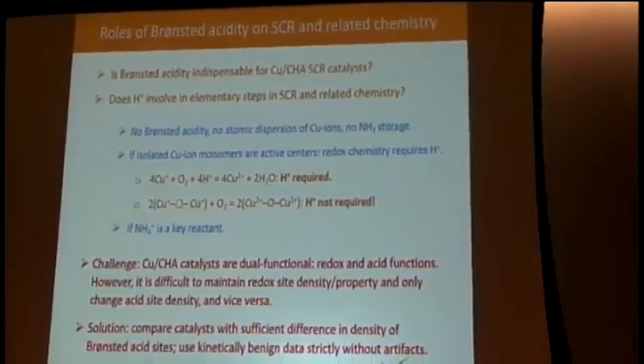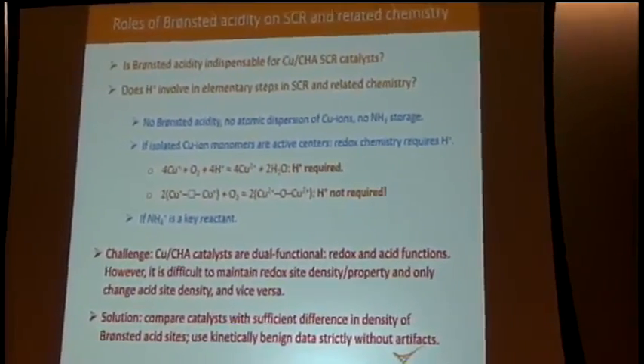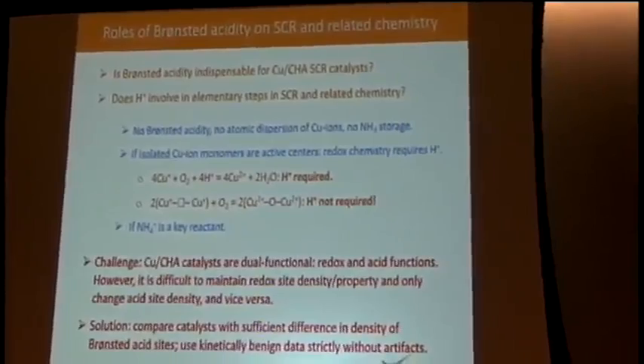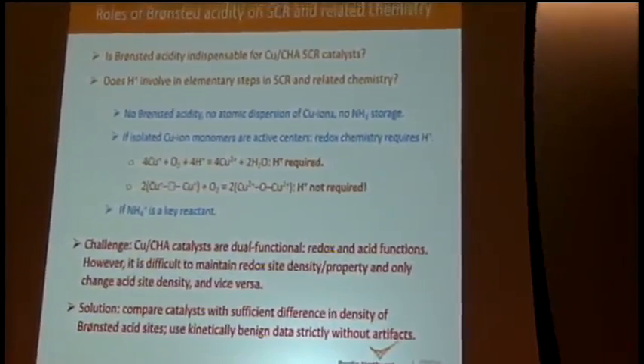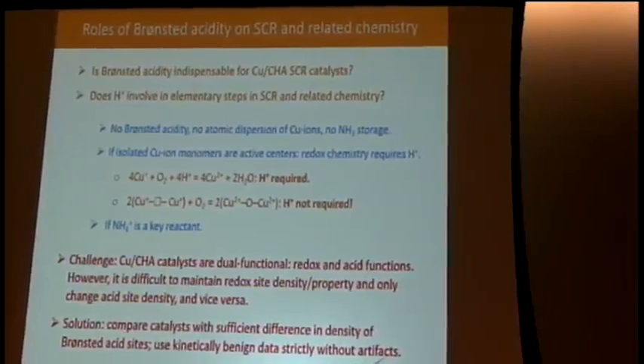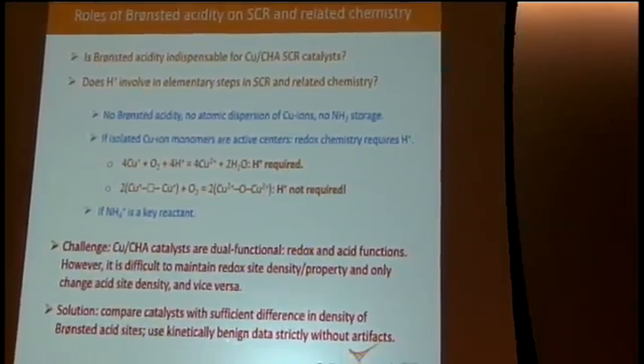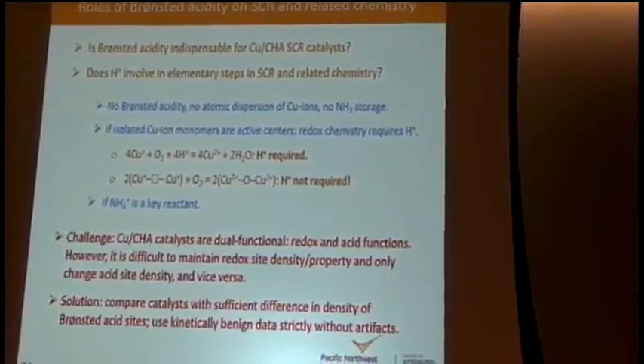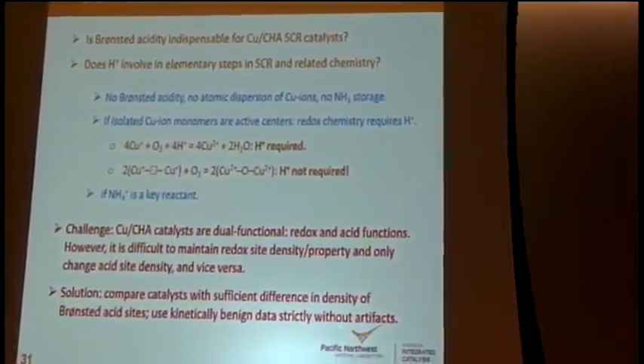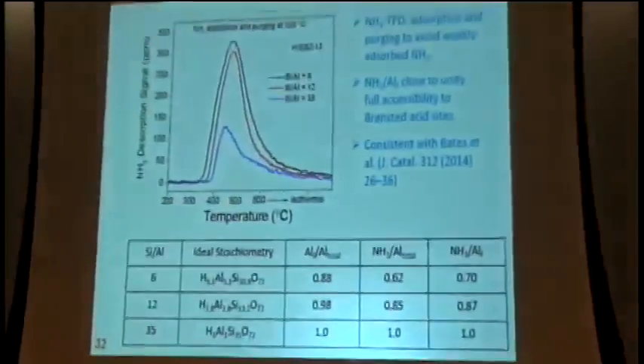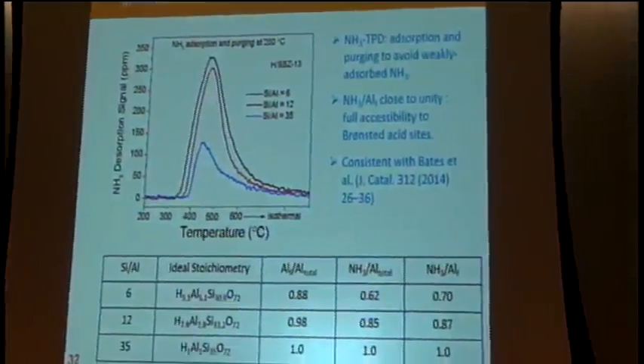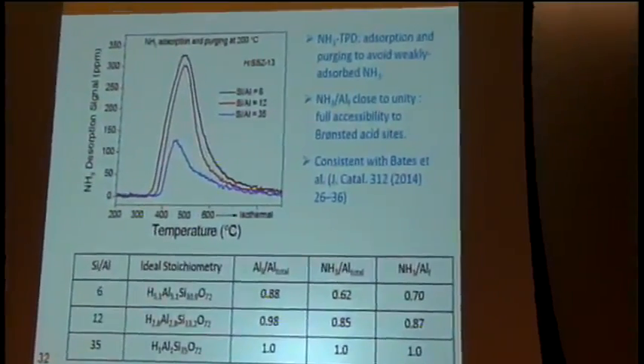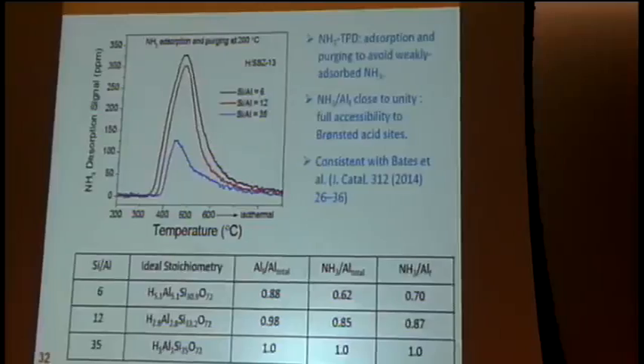So what we did is to compare catalysts with sufficient difference in the density of Brønsted acid sites, and we only use kinetic data being within the differential regime to do our comparison. This slide shows the ammonia TPD, and I will not go into the detail, just to show that we use this technique to quantify the number of Brønsted acid sites in each unit cell of our catalyst.